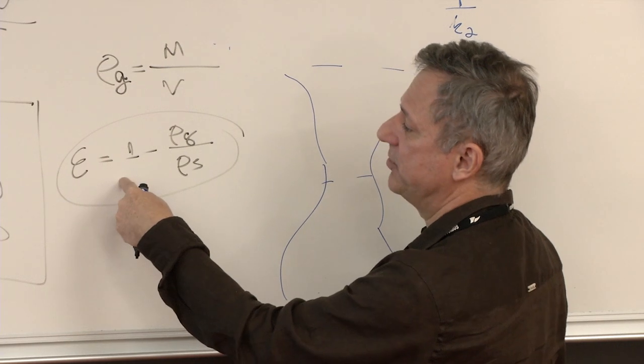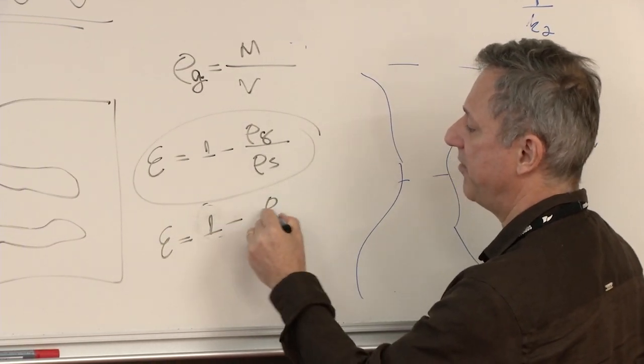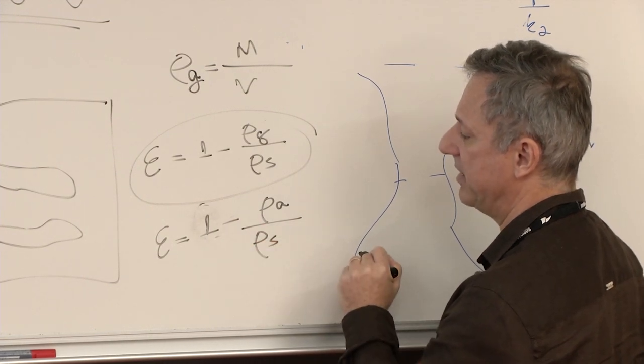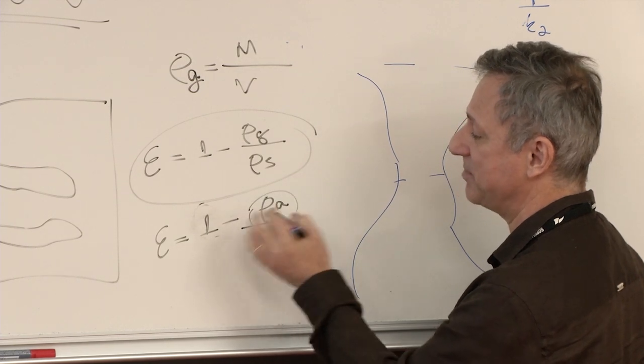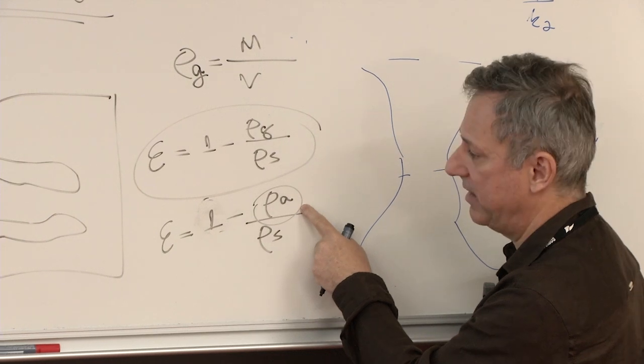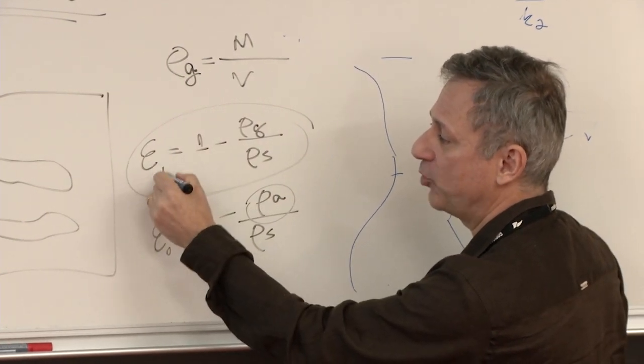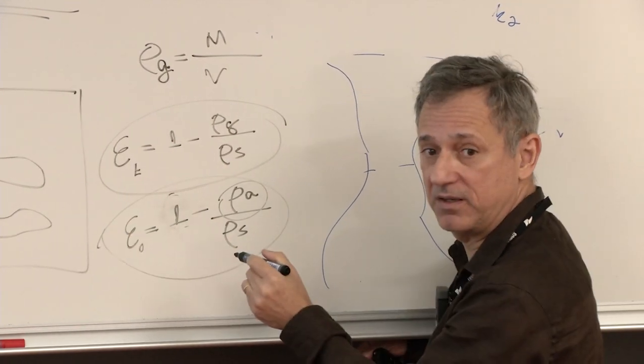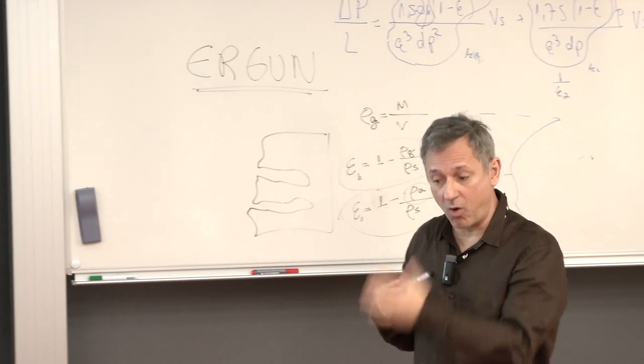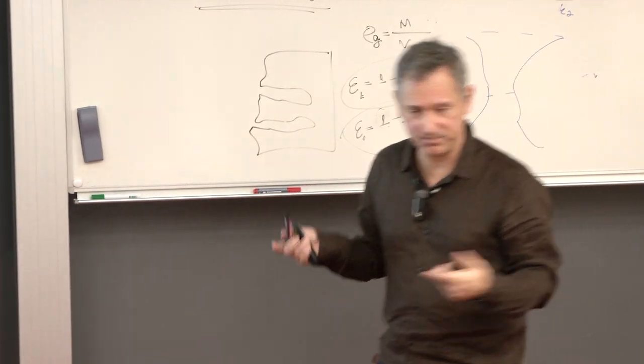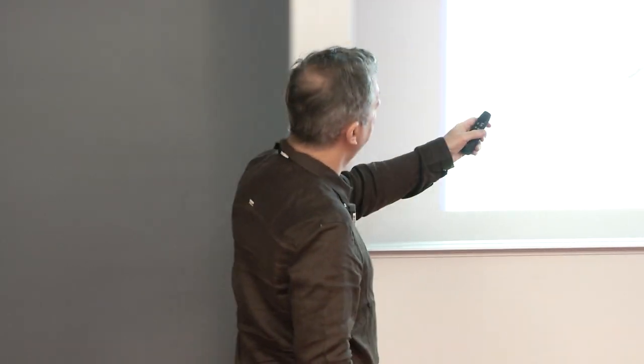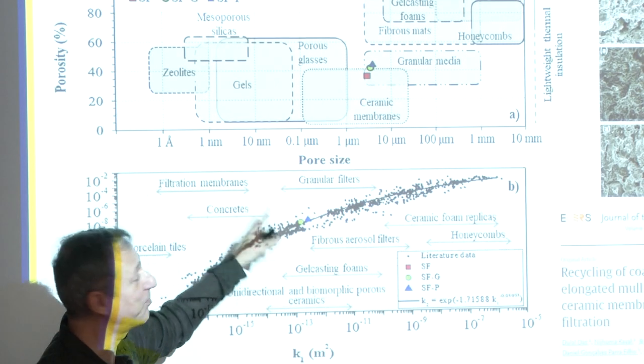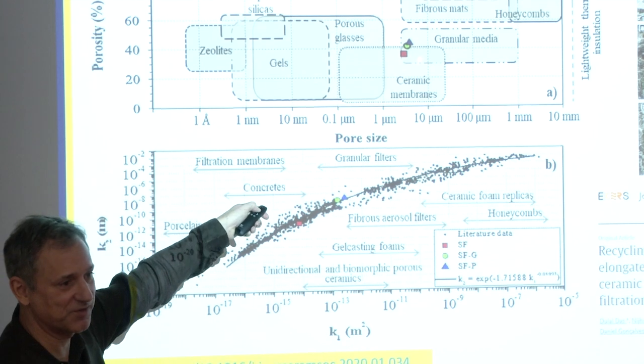That one, I didn't use this equation. I used a similar one: one minus apparent density divided by solid density. This one was by water immersion with Archimedes. This is the open porosity; the other is the total porosity. In that map, I put this one. But not all the open porosity is used for permeation. And if you see, you have a very similar range, but you see very different permeation levels. So probably a great part of that porosity is closed for permeation. It's open for the water to enter, but it's not interconnected from one side to the other side. So for filtration, this is very bad.